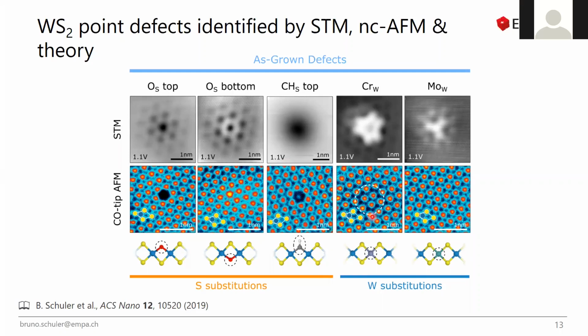Okay, thank you. Okay, so and then the other type of defects we see frequently is transition metal substitution. And this simply comes from the precursors, so they are not 100% clean, but they have impurities on the order of parts per million, and this also just ends up in your material. So for instance, chromium or molybdenum replacing a tungsten atom. And this one here, we talk a bit later, which kind of has a funny STM image, looks like a dark hole. We actually could assign to a carbon type of impurity.